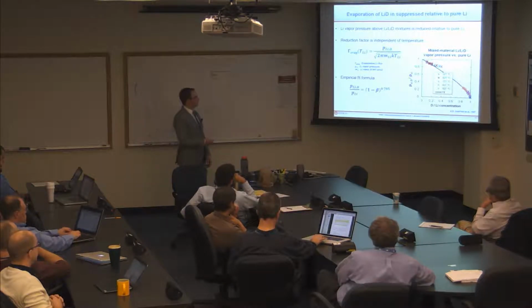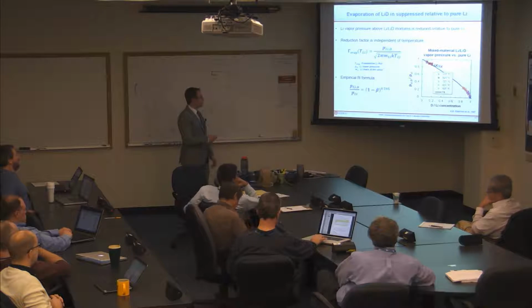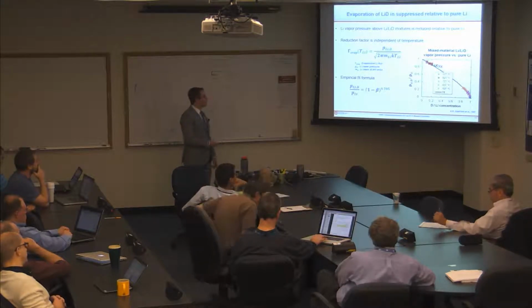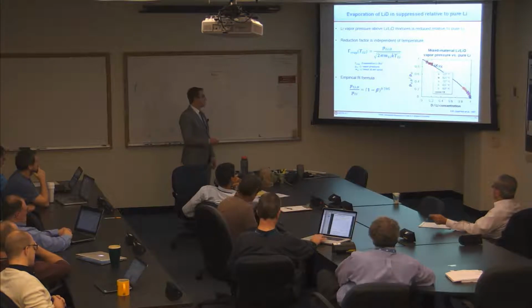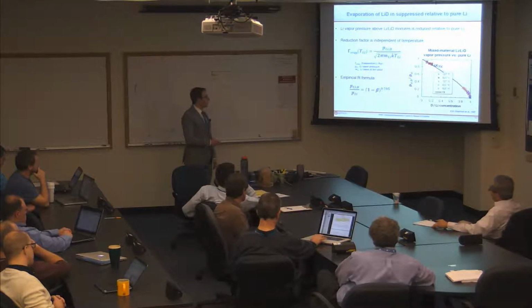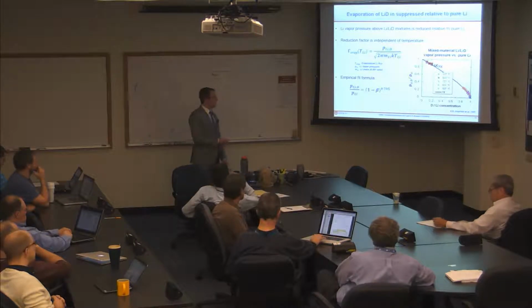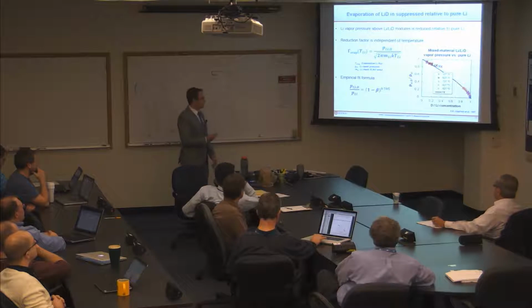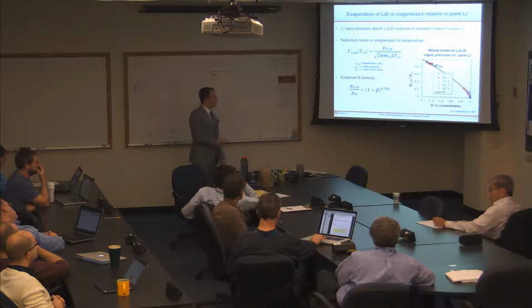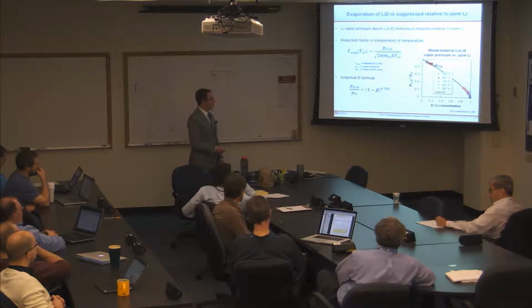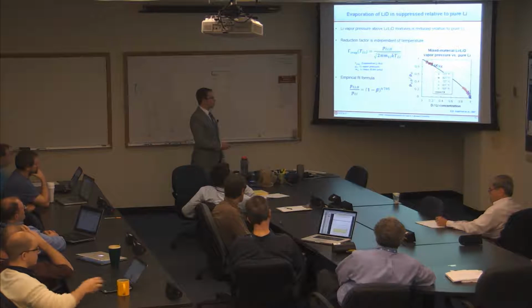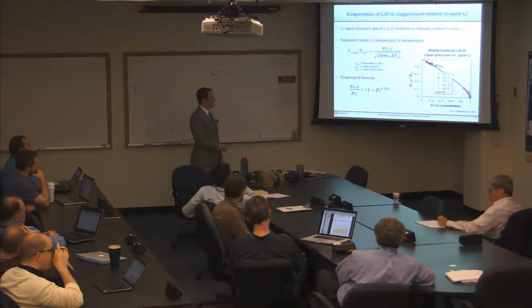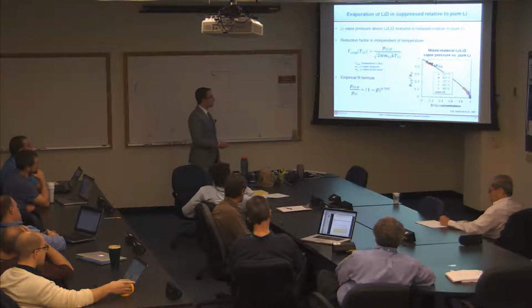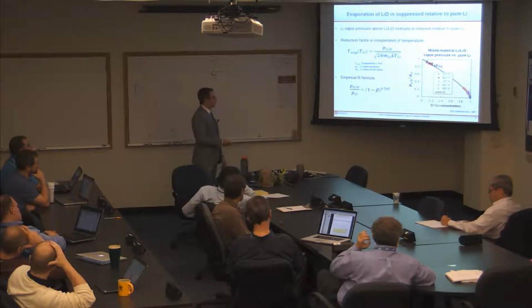The predicted evaporative flux of lithium from the surface is given by the so-called Langmuir law equation, and it's just equal to the vapor pressure divided by the square root of 2 pi mkT. M is the lithium mass, T is the lithium temperature. Over here on the right, I've plotted the vapor pressure of lithium above a mixed material lithium deuterium layer divided by the anticipated vapor flux from a pure liquid surface as a function of beta. The different symbols are different temperatures, and it's pretty much constant as a function of temperature, this reduction, which is good because it means you can fit something very simple to it.